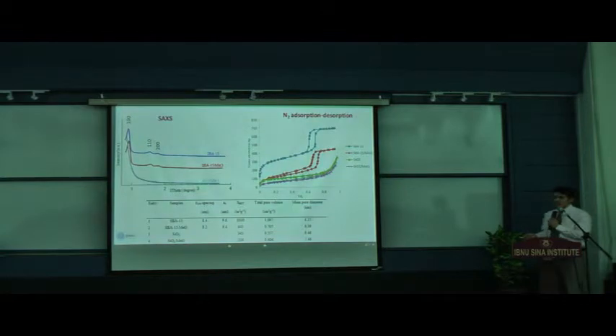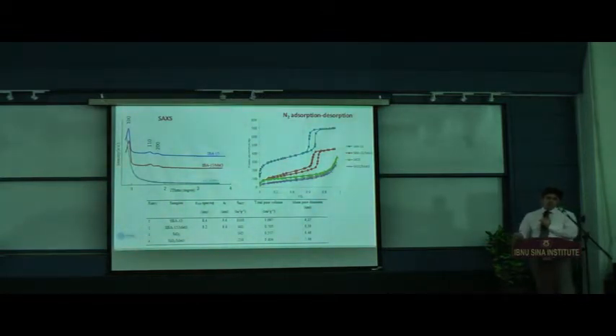So we started this chemistry, and of course it was characterized with the help of too many techniques. When we are talking about the porosity, mesoporous, we have to be careful about the size. MCM-41 is silica material. SBA-15 is also silica material, but different channel size. So we characterize the material. I'm not going to explain one by one. We just make sure that it is mesoporous and has surface area, total pore volume, mean pore diameter, and everything was checked.